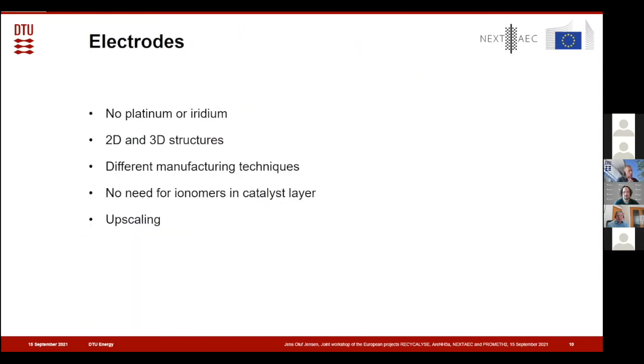Looking briefly at the electrode development, rule number one: no platinum or iridium. We are looking at both two-dimensional and three-dimensional structures. Actually, all the electrodes are three-dimensional, but some are based on a plate where you add some catalytic layers, a perforated plate. That is a common way to do it. But we're also looking at the 3D structures where you can get a much higher surface area and utilization of the membrane. There'll be no blind spots. So that is under development. We are pursuing different manufacturing techniques. DLR is using plasma spraying, and the University of Leuven is using other techniques on substrates and even 3D printing of the electrode. So that's also very exciting.